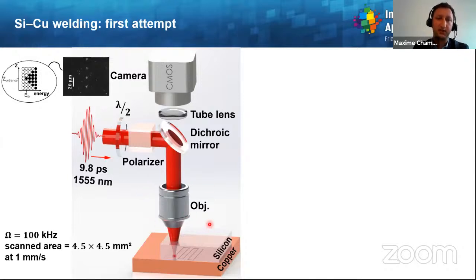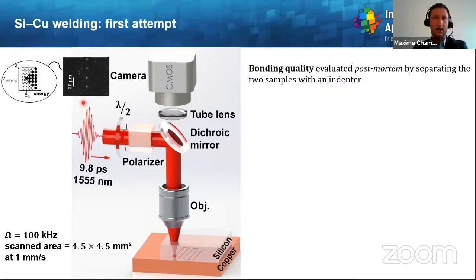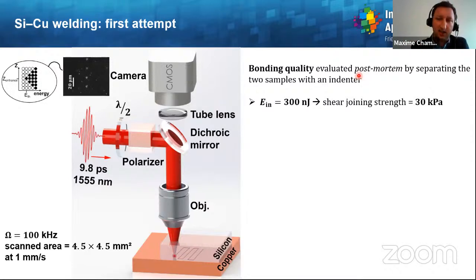And this objective lens is also part of a reflection microscope, which enables us again to position the geometrical focus with respect to the silicon entrance surface. Then after the laser processing, we evaluate the bonding quality in a post-mortem way by separating the two samples with an indenter. And when we try with a relatively intermediate, let's say, input pulse energy of 300 nanojoules, then we can measure a shear joining strength of 30 kilopascal.